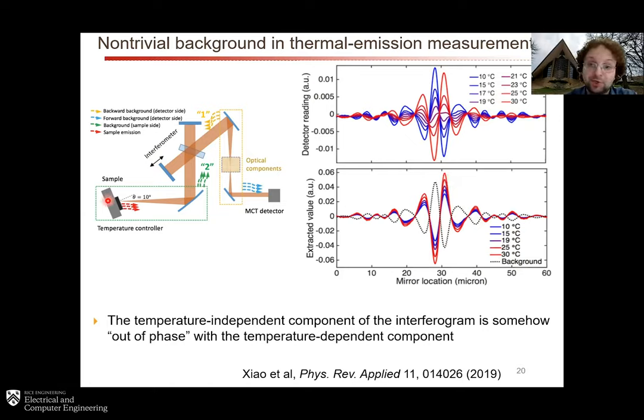And by looking at which part of the interferogram was staying constant and which part was changing as a function of temperature of our sample, what we observed is that actually the sample contribution was always increasing with temperature like we would expect, but then there was this cancellation happening with the background as a result of the background emission from the optical components, and they were effectively canceling out on the interferometer, which we found quite strange because, of course, these are all incoherent effects.